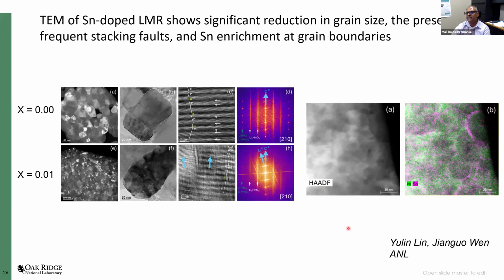So adding tin to this material seems to go into the lattice, but I think that what happens is these small nano domains are trying to purify themselves. And as they try to purify themselves, they are pushing the tin out to the grain boundaries. This leads to a significant reduction in grain size. There is an increase in the amount of stacking fault densities.